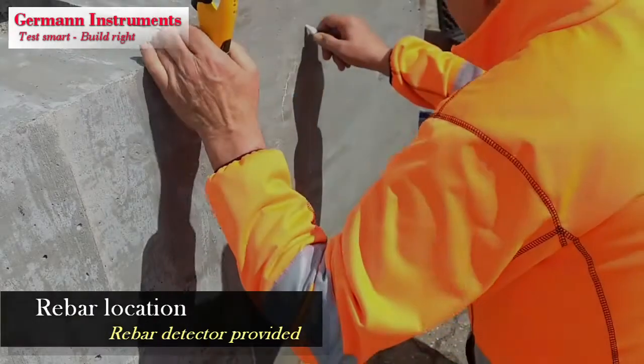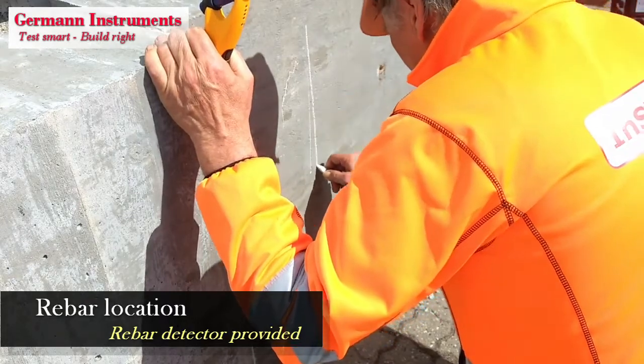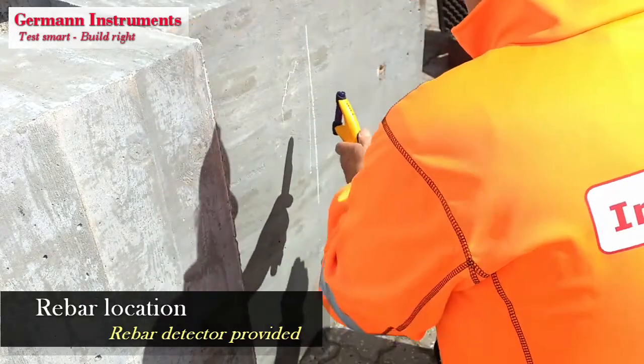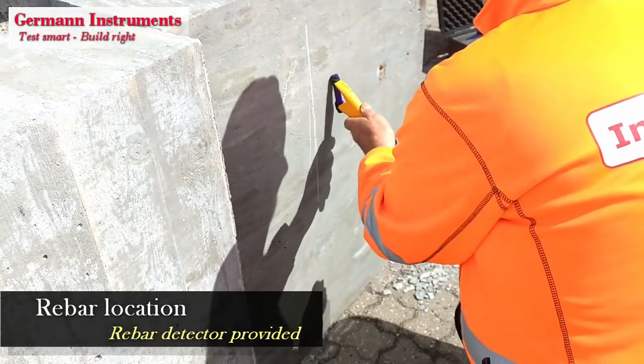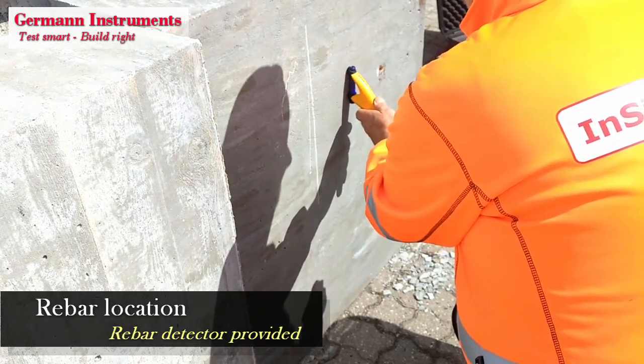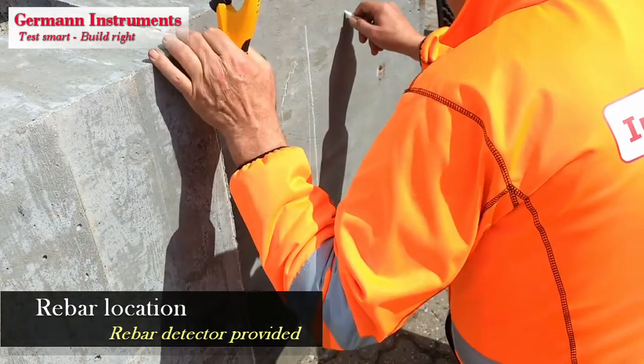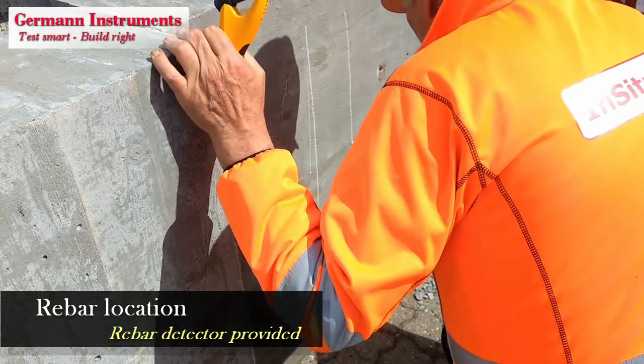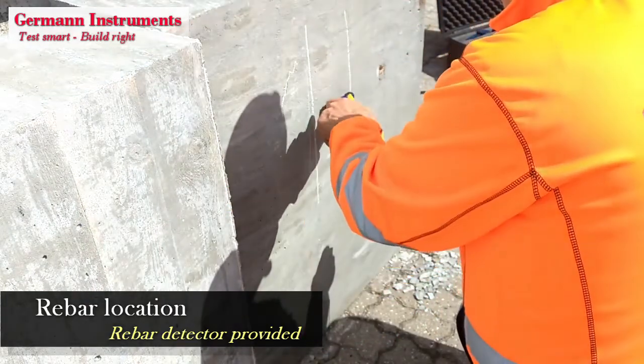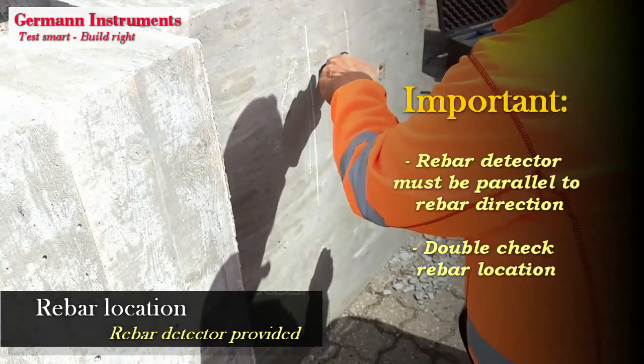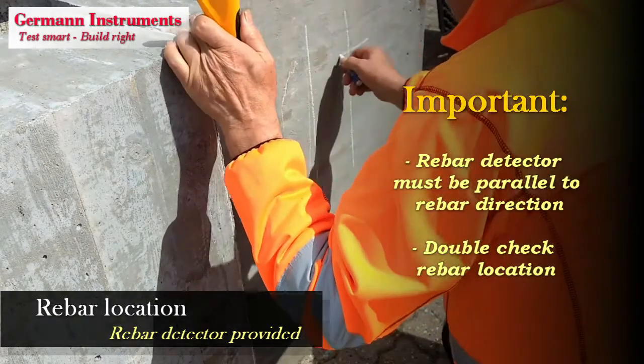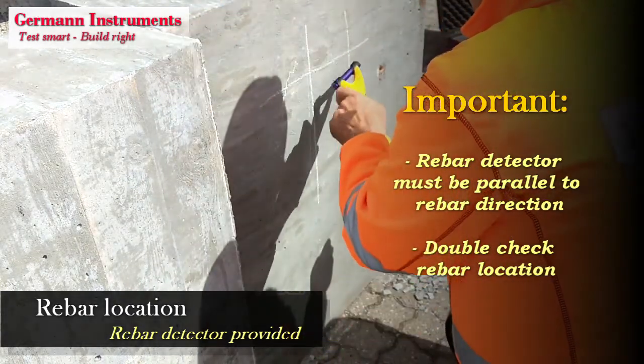The reinforcement is located. The supplied detector can be used up to a depth of approximately 70 mm, otherwise a cover meter must be used. The reinforcement must be at least 10 mm away from the failure zone. This small distance makes the CAPO-Test applicable even in highly congested reinforcement areas. The test location is selected in the middle of the reinforcement mesh.